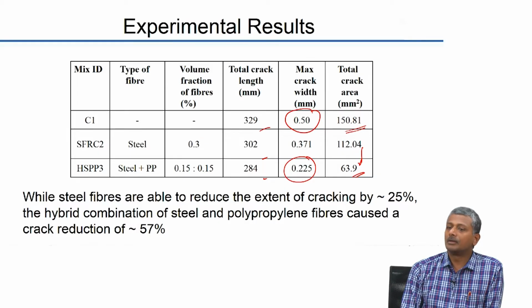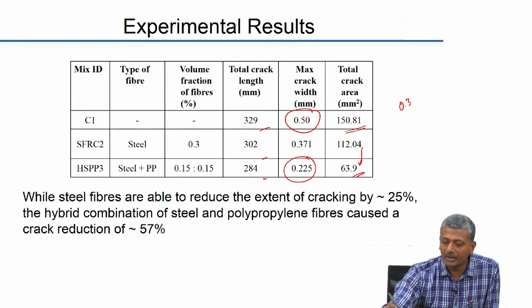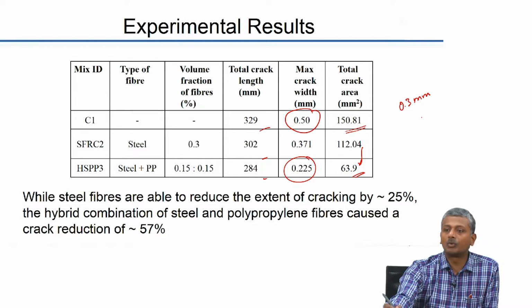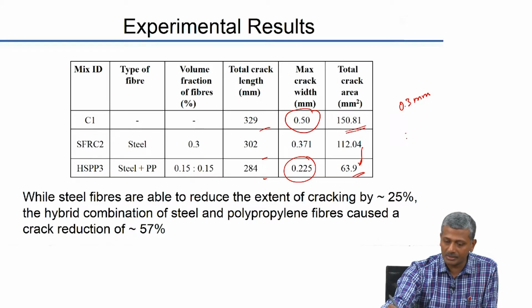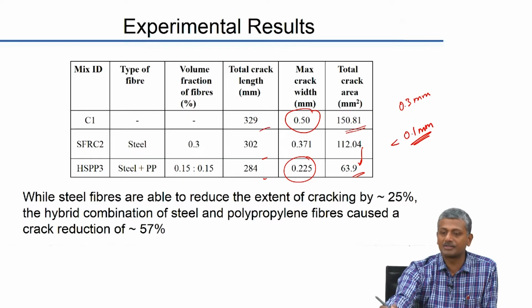Yeah, 0.3 millimeter in a... What type of exposure? Mild or moderate exposure, but when you go to very severe or extreme conditions, you need to restrict your crack widths to 0.1 millimeter. So, crack width should be less than 0.1.